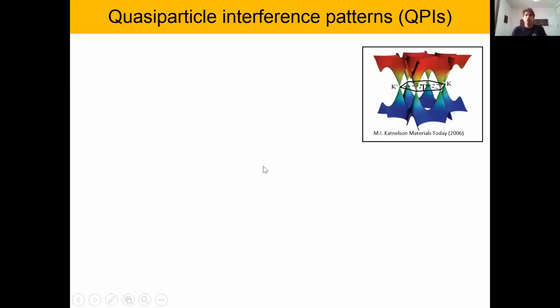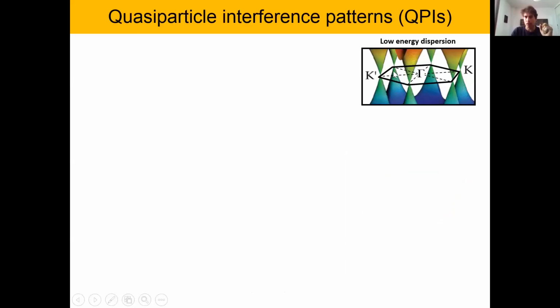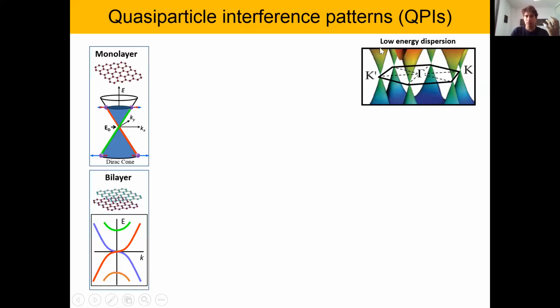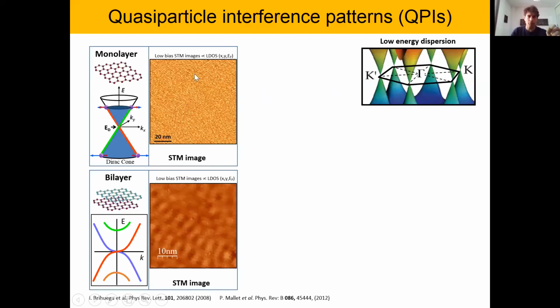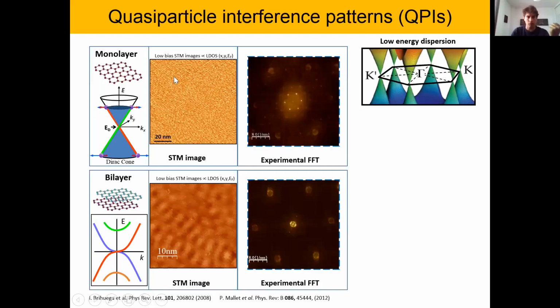Okay, so we will use the same approach to probe the properties of graphene, and here is the band dispersion of graphene, with the Dirac cones at the K and K prime points. So this is the complete band dispersion. If I zoom in for low energies, we see very nicely how the Dirac cones appear both at the K and K prime points of the Brillouin zone. Of course, the shape of these Dirac cones will be different for monolayer and bilayer. In monolayer, they are linear, so we have massless Dirac fermions, and in bilayer, you have a parabolic dispersion, which means you have massive Dirac fermions. And of course, we also have colors here in the bands, which account for the additional degree of freedom that quasiparticles have here, which is the pseudospin. Okay? So now we do these QPI measurements, both on monolayer and bilayer graphene, and to analyze those QPI patterns, the standard way of doing it is to get the Fourier transform, the two-dimensional Fourier transform.